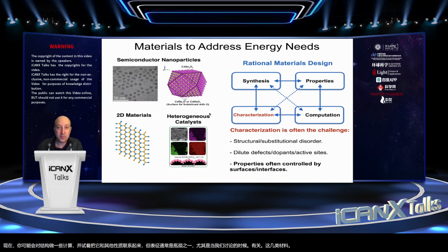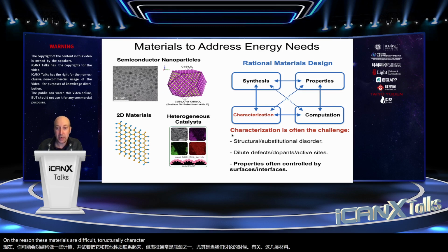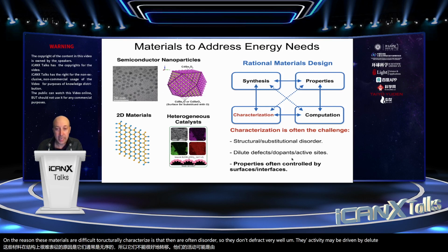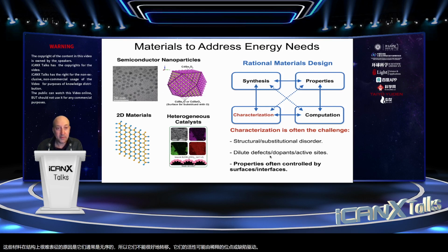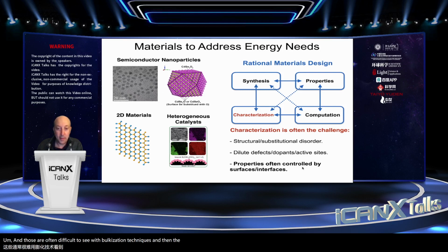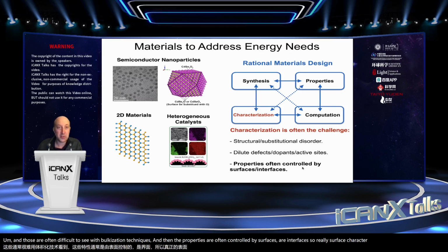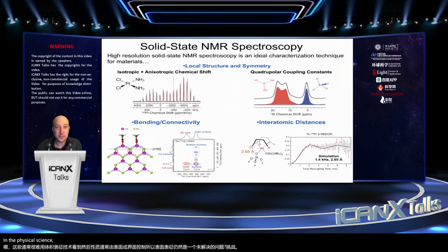The reason these materials are difficult to structurally characterize is that they are often disordered, so they don't diffract very well. Their activity may be driven by dilute sites or defects, and those are often difficult to see with bulk characterization techniques. And then the properties are often controlled by surfaces or interfaces. So really, surface characterization is still an unresolved challenge in the physical sciences.